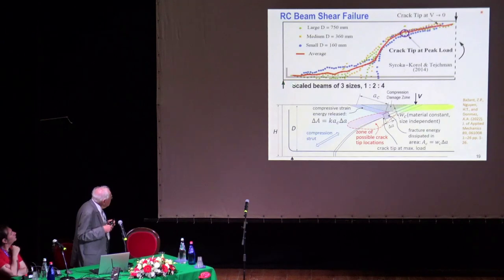They are plotted in dimensionless coordinates. And what is noteworthy is that the cracks are similar, which is essential for validity of the size effect law. And maximum load always happens around here. Crack starts propagating here. And when it reaches this length, the geometry changes from negative to positive, and there is dynamic failure. Now the mechanism we understand. So the crack starts by tension, mode one. That can be modeled by linear fracture mechanics or, better, a cohesive model.